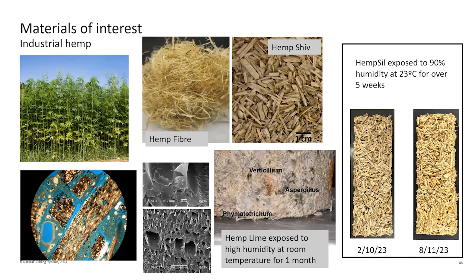There are 2 parts to the hemp plant. So your old hemp plant here, after it's been retted, you can take off the fiber and you're left with the woody core inside, which is what we call the shiv, which is this material here. And that is the material which we use to manufacture our hemp sil. The hemp fiber is really useful for making fibrous insulation, very low thermal conductivity insulation.